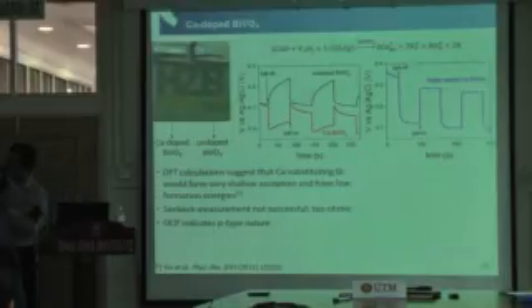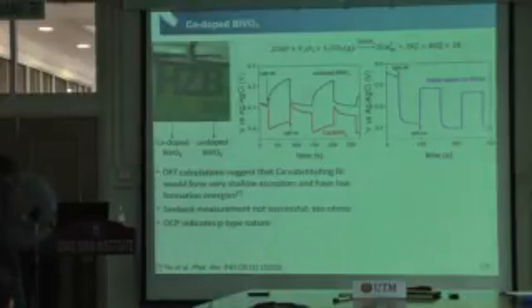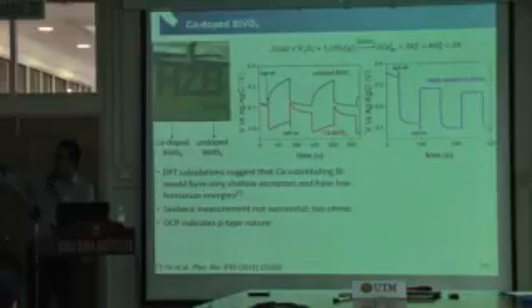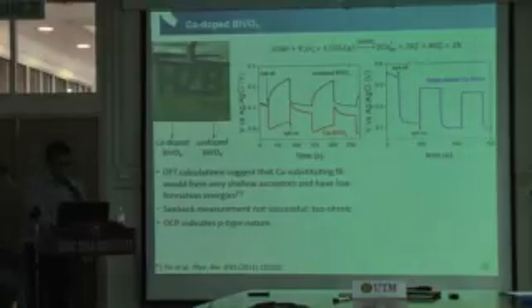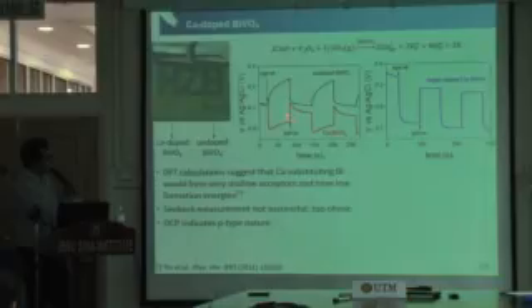So the change here is then reflected over here, right? Am I making myself clear? So for an n-type semiconductor, you would expect it to become more negative as a potential. This is the potential scale. So that's negative, that's positive. Potential scale refers to energy. So for an n-type semiconductor, you would expect it to become more negative if you turn on the light. And it turns out to be the case here for an undoped bismuth vanadate. As you turn on over here, it becomes more negative. As you turn off the light, it becomes more positive.